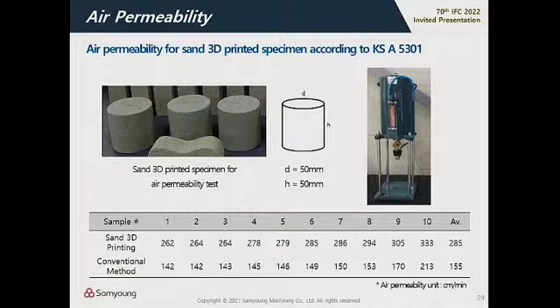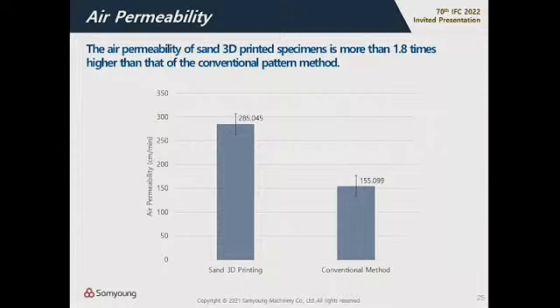We tested air permeability for the sand 3D printed specimen according to the standard. This picture shows the actual sand 3D printed specimen for the air permeability test. And this is the test equipment. This table shows the test results for 10 different specimens of 2 different methods. The results show that the air permeability of the sand 3D printed specimens is more than 1.8 times higher than that of the conventional method. The left-hand side is the sand 3D printing result, and the right-hand side is the conventional method result.